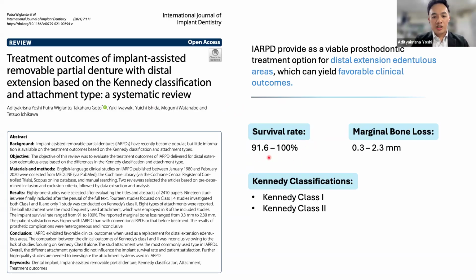from 91.6% to 100%, and the marginal bone loss ranged from 0.3 to 2.3 millimeters. And based on our analysis in this systematic review, we concluded that IARPD can provide us a viable prosthodontic treatment option for distal extension edentulous areas, which can yield favorable clinical outcomes.